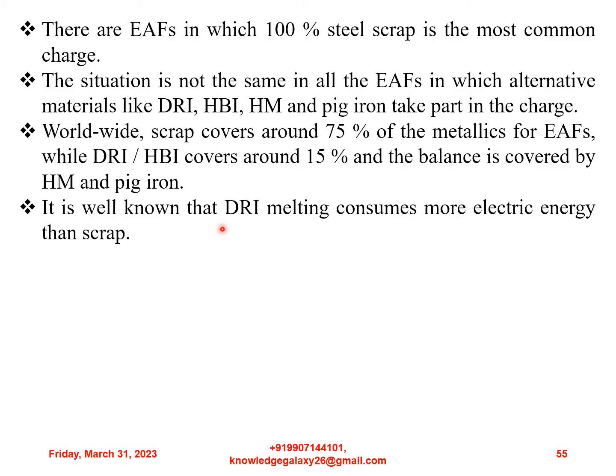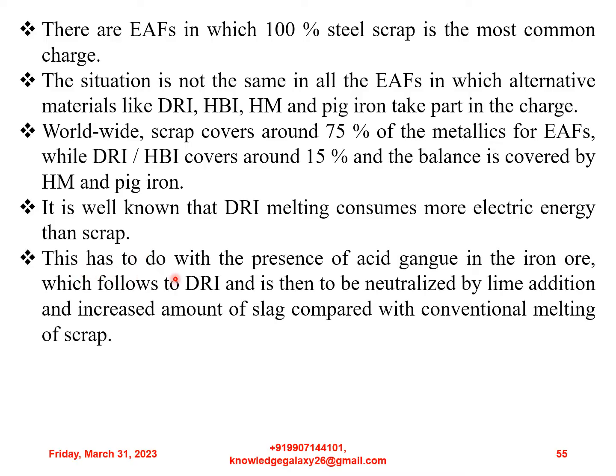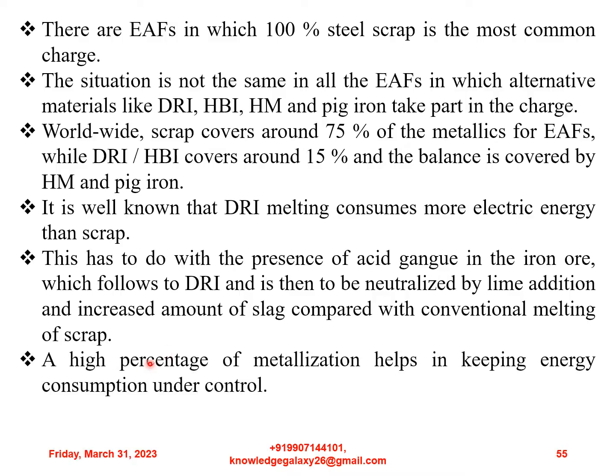It is well known that DRI melting consumes more electric energy than scrap. I repeat, this is an important aspect. This has to do with the presence of acid gangue in the iron ore, which carries over to DRI and is then neutralized by lime addition, and an increased amount of slag compared with conventional melting of scrap. A high percentage of metallization helps in keeping energy consumption under control.